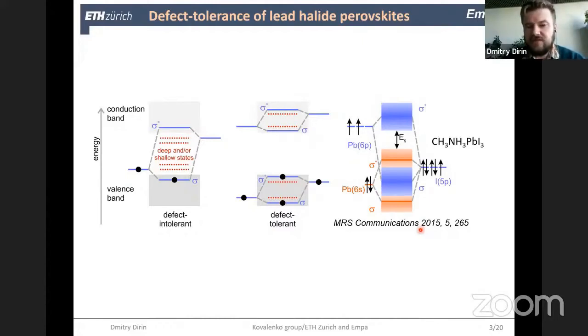And in 2015, it was shown that lead halide perovskites represent this case, at least partially, because the valence band and conduction band in this case are formed by different hybridized orbitals. So the top of the valence band is formed by the antibonding orbital of iodine and lead, and the bottom of the conduction band is formed by still antibonding orbitals of lead and iodine, but due to some spin orbit coupling effects, the bottom of this band is quite low energetically, and this means that